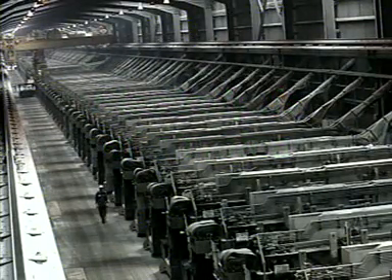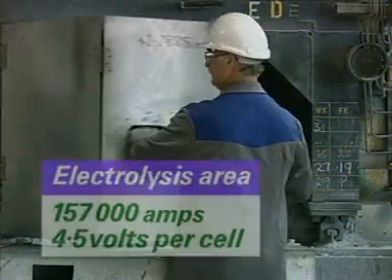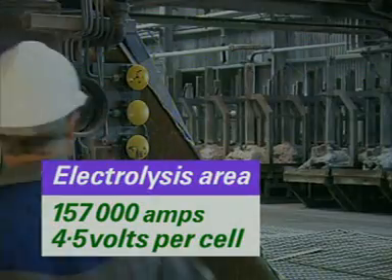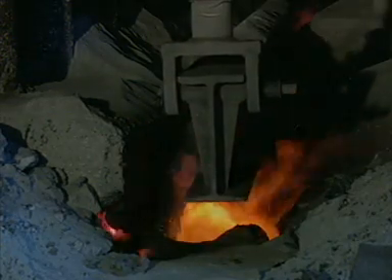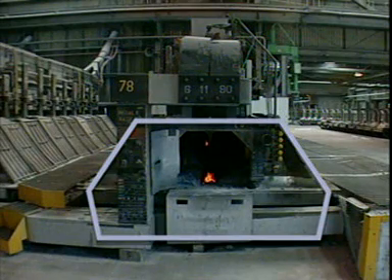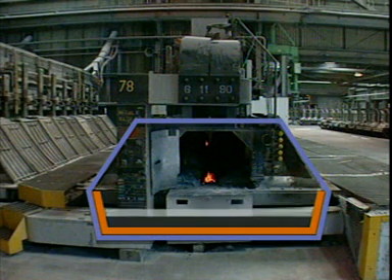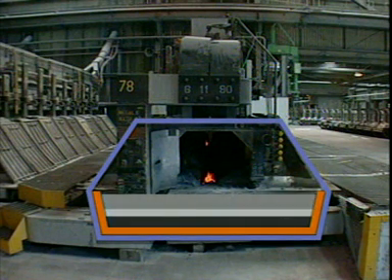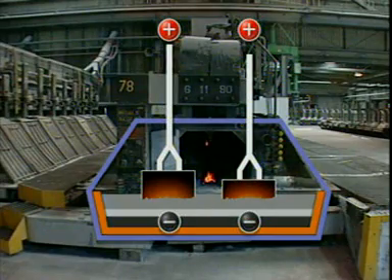This is one of the four rows of electrolysis cells where the electrolysis takes place. The current is about 157,000 amps at 4.5 volts. This is one of the 312 cells. The electrolysis cell consists of a rectangular steel shell lined with heat-resistant brick and then carbon. Each cell is filled with molten cryolite, and the aluminium oxide is dissolved in it so that it conducts electricity. 18 carbon anodes dip into the electrolyte.